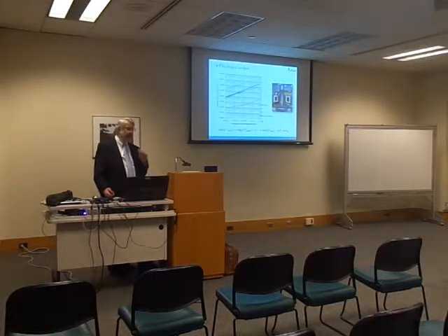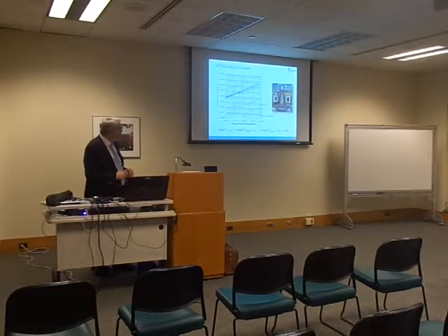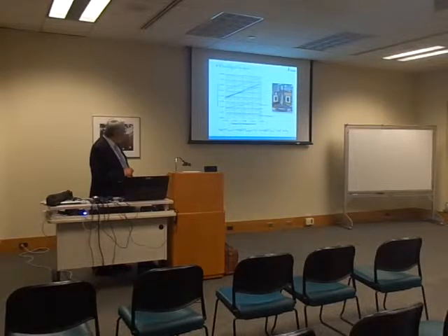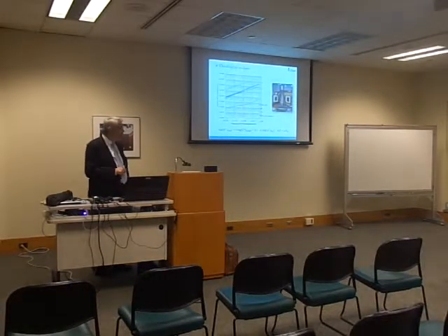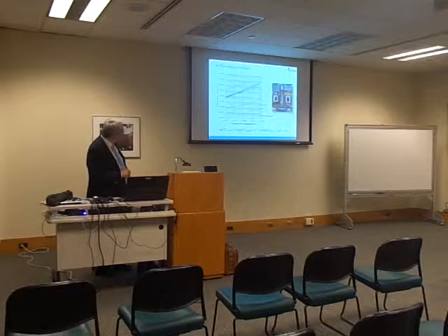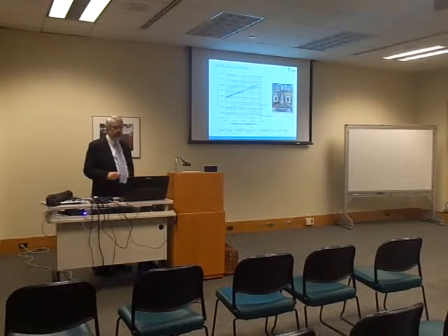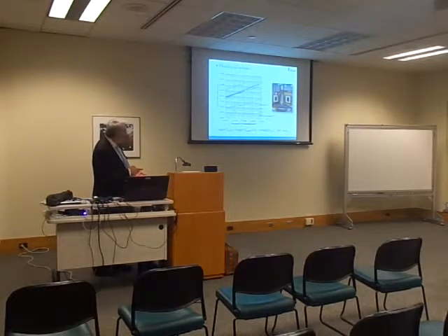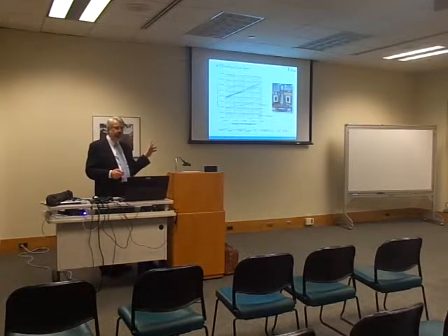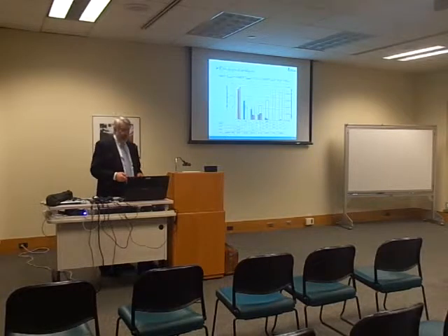Now, if you look at a given temperature, then it becomes more interesting, because what I'm showing here is the original aged bitumen, the rejuvenator in terms of its own stiffness, and what happened when we mixed them, both theoretically and via the measurement. So you have a stiff material, and you try to reduce its stiffness by putting something soft and mixing it. And that's what it is. That's the type of techniques that we'll speak about in this lecture. There are other ways to rejuvenate. We'll do it next time. Some more technicalities.